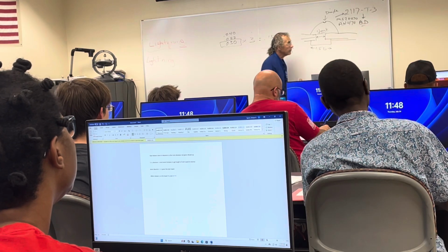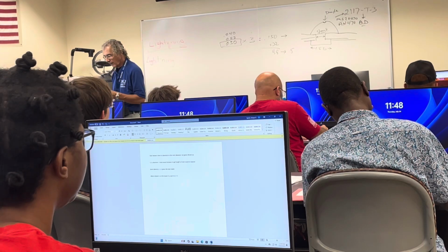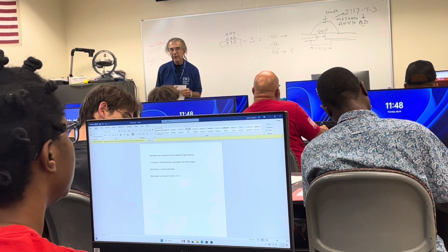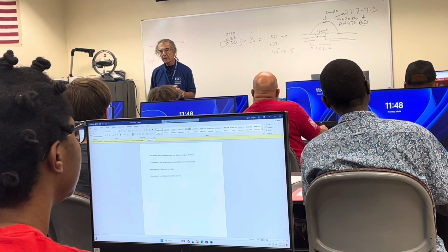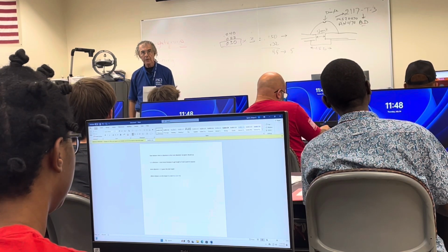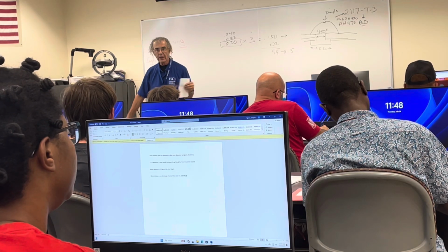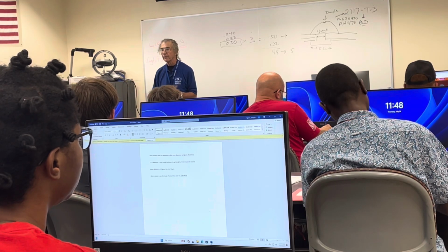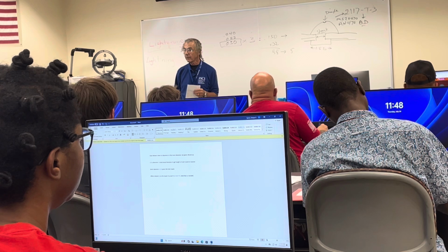When it's written out, it'll have the letter designation AD. What that means is we can pull these out of the bucket and dry them, because they are already properly tempered and heat treated at the factory. And they don't age or work harden until you buck them. Once you buck them, you induce work hardening into them.